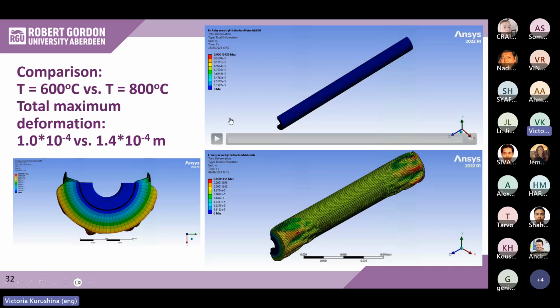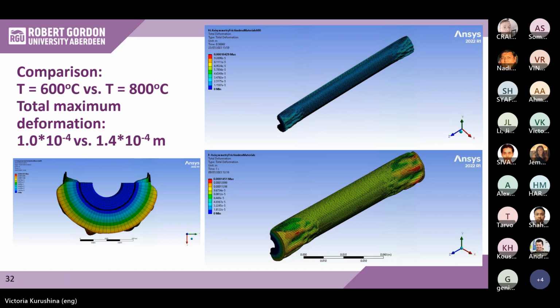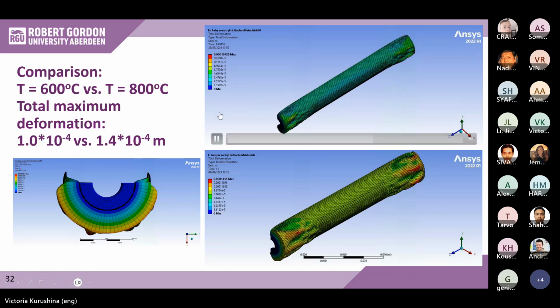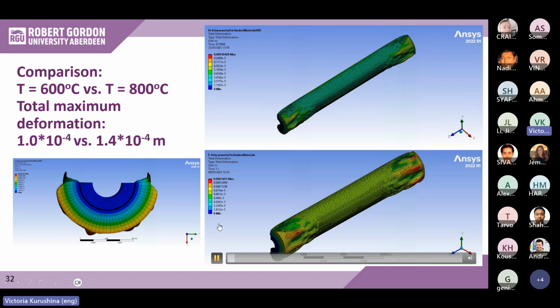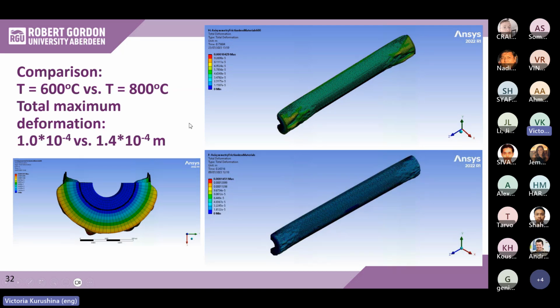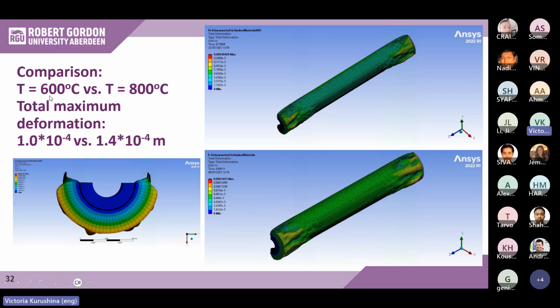So in these videos, you can see the difference in how the total deformation develops for 600 degrees Celsius. This is on the top. And for 800 degrees Celsius, this is what you have already seen. The difference between expansion at 600 degrees and 800 degrees is about 1.5 times. This is the maximum total deformation observed in the model.